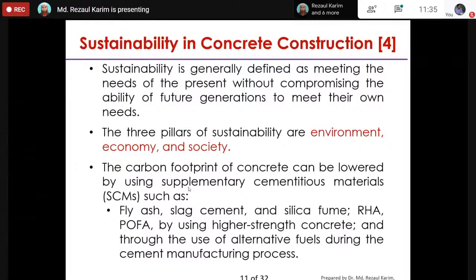The carbon footprint of concrete can be lowered by using supplementary cementitious materials. This has also been well proved by researchers, because fly ash, slag cement, silica fume, rice husk ash, and palm oil fuel ash can be used as supplementary cementitious materials, and these can also be used for high strength concrete. Alternative fuels can also be used during the cement manufacturing process.